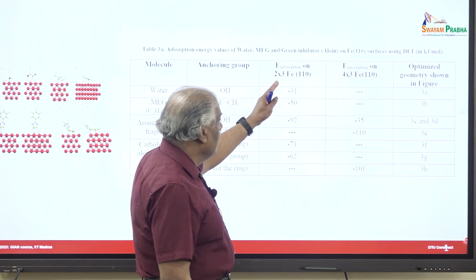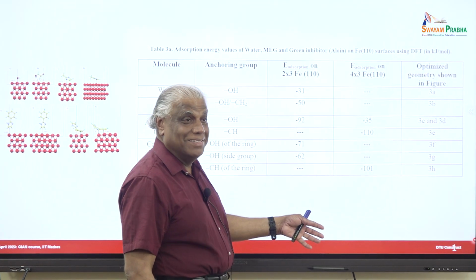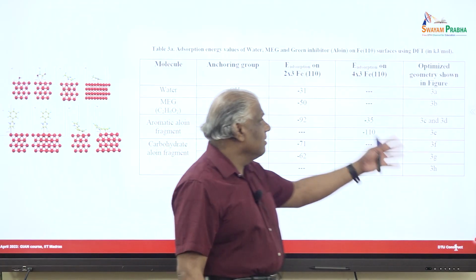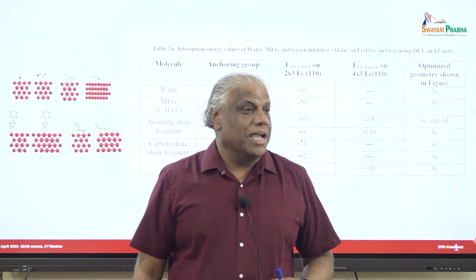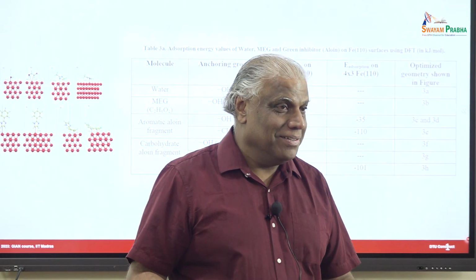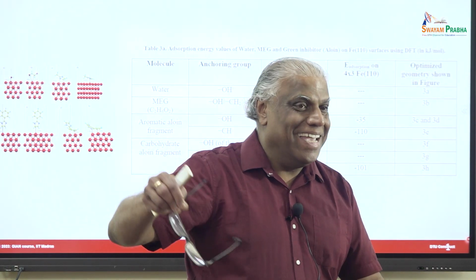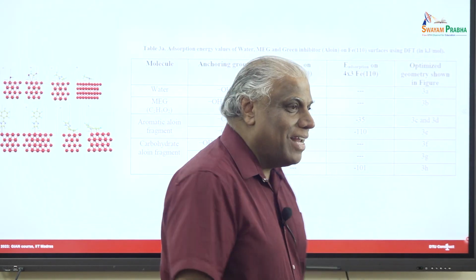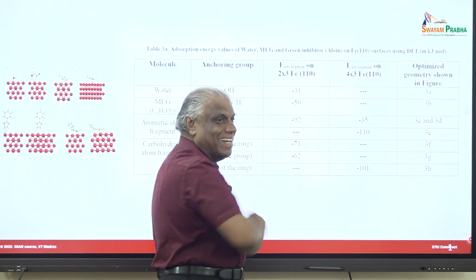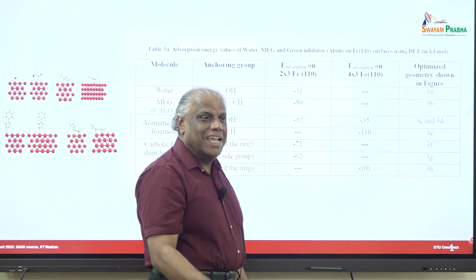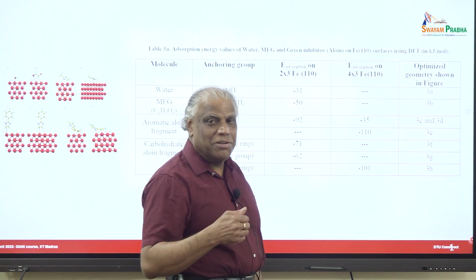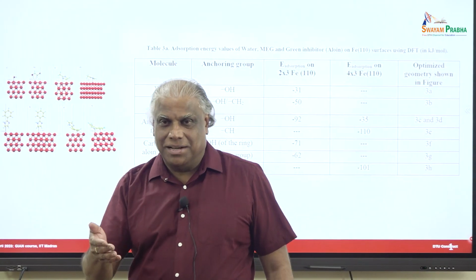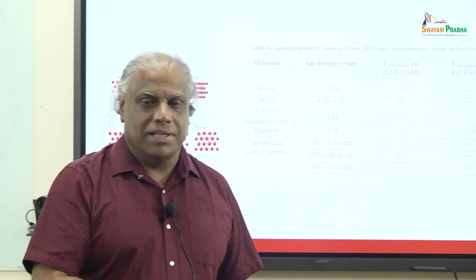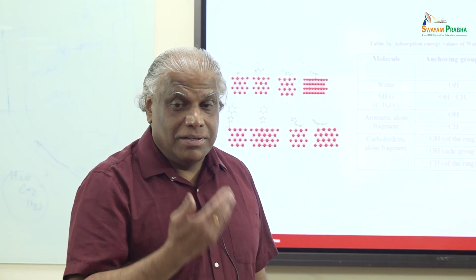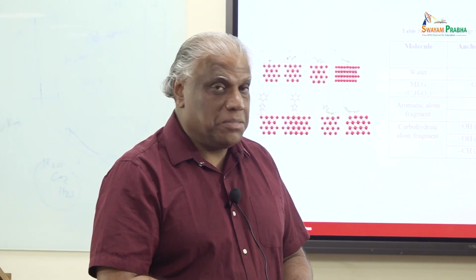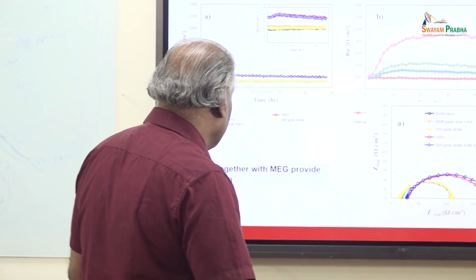I have another table where we also do the absorption on iron carbonate. We do the same molecules and look into how they absorb on iron carbonate. Why is that important? As I mentioned earlier, iron carbonate is the scale. If the energy of absorption to the scale is better than this, then there is a chance that once the scale starts forming, this molecule will be lost because it will be absorbed onto iron carbonate or iron oxide. So we also do the absorption energy calculation for the iron carbonate scale, and this is a really powerful tool. It helps a lot, especially for green inhibitors, to screen the different molecules. So that's what is shown here.